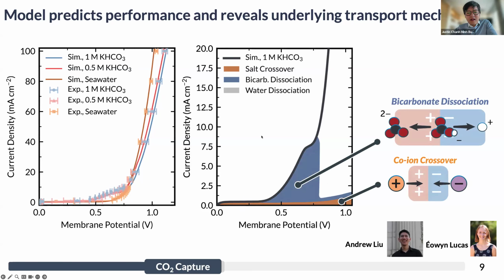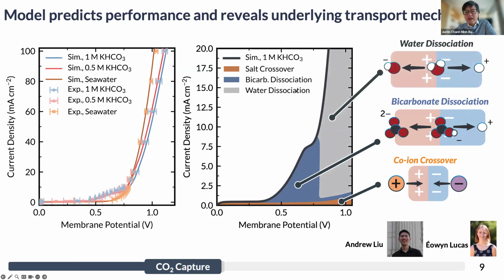We see that there is actually a very non-negligible contribution of electric field or catalytically enhanced bicarbonate dissociation, which results in this first takeoff at about half a volt. So bicarbonate splitting into protons and carbonate. And then finally, we see the standard water dissociation takeoff that we expect. And so that basically tells us that this hump feature is actually due to a field enhanced bicarbonate dissociation that occurs at around half a volt, which is consistent with the pKa of that buffering acid.